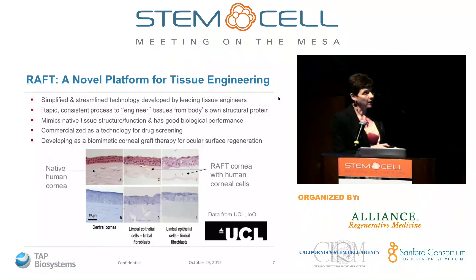This image shows a normal human cornea with a stroma containing fibroblasts and a stratified epithelial layer on top. Here is one made using the RAFT process: limbal fibroblasts seeded on the surface with epithelial cells, which over time in culture form a stratified epithelial layer. In terms of biomarkers, structure, and function it is very similar — if you wound it, it will heal, and it will continue to heal if wounded multiple times. This is being taken forward into a first-in-man safety study in 2014 for patients with limbal epithelial stem cell failure caused by chemical or thermal burns.